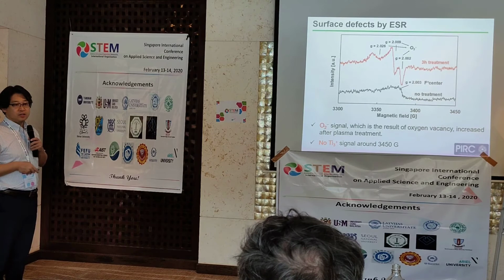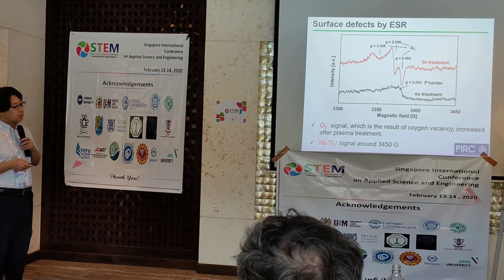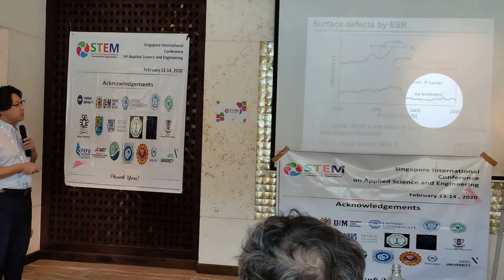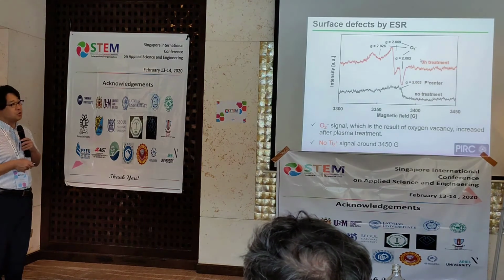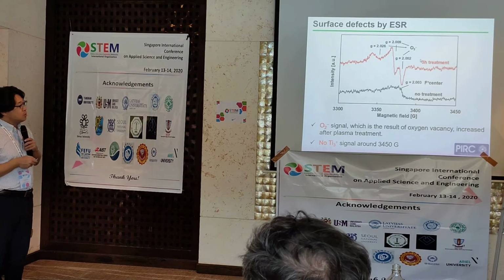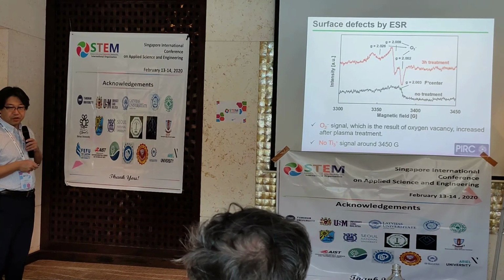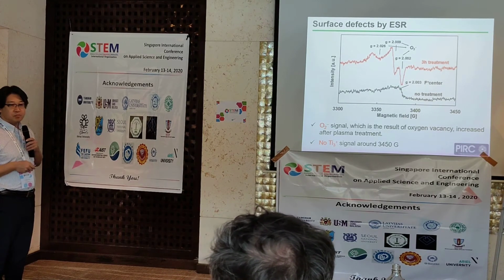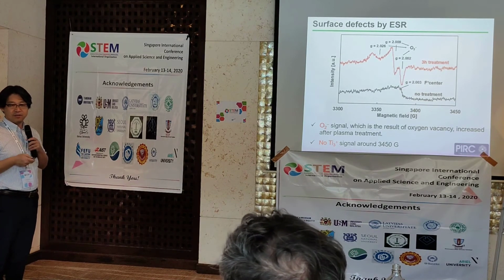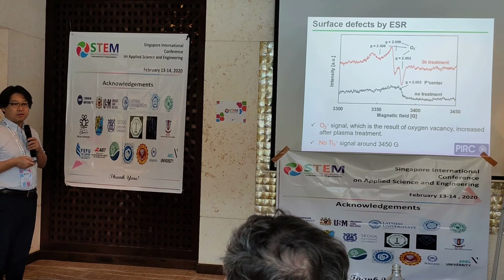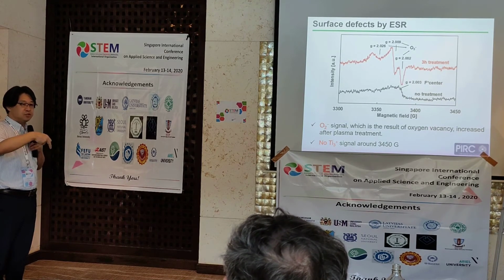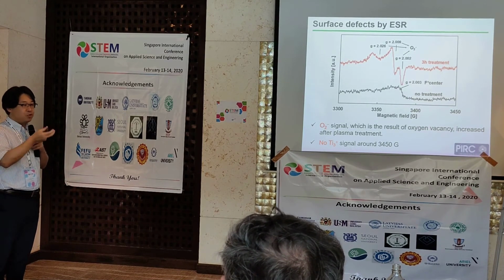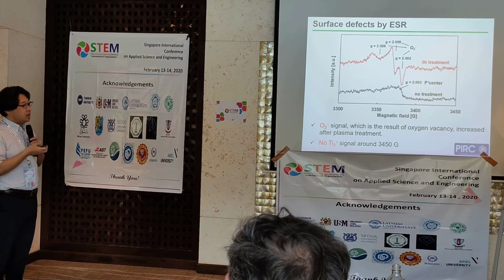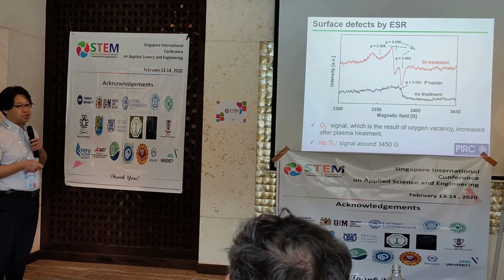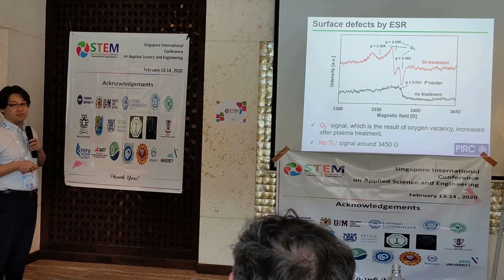So we checked ESR spectra. This black line is no treatment and the red line is the plasma-treated sample. We get the O2 minus signal. This O2 minus means the oxygen vacancy of our sample. An oxygen molecule comes to an oxygen vacancy, then couples to the electron. Then our sample shows the O2 minus signal in this ESR spectrum.